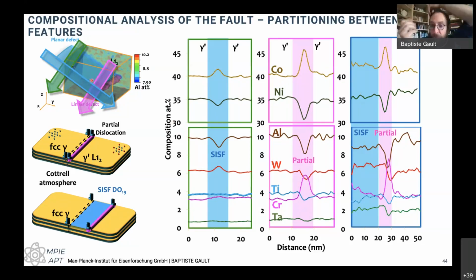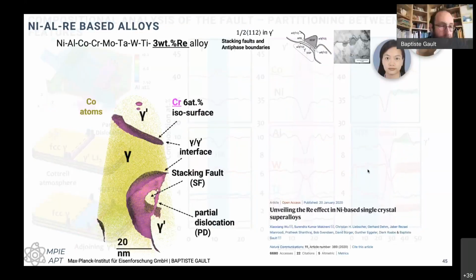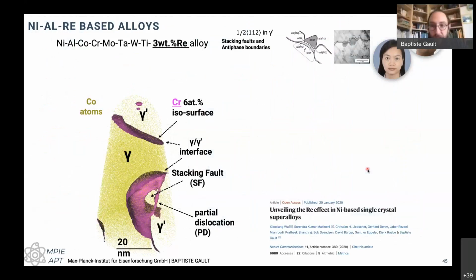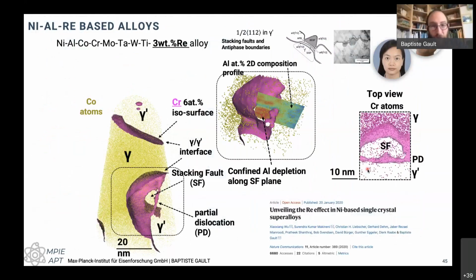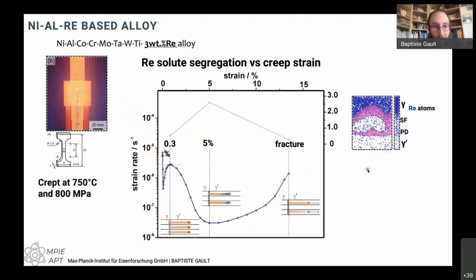So we see a segregation of cobalt and tungsten that would be expected. Why we propose this mechanism is because when we look through the fault, we don't see any depletion of tungsten on either side, right? So the tungsten must be coming from somewhere else. And what we interpreted is that the dislocation as it moves actually facilitates transfer of tungsten from ahead of the partial directly onto the fault. We did a lot more work on these things, looking at rhenium, for example, in some of these alloys, but I'll probably skip that and can talk about it later if you want.